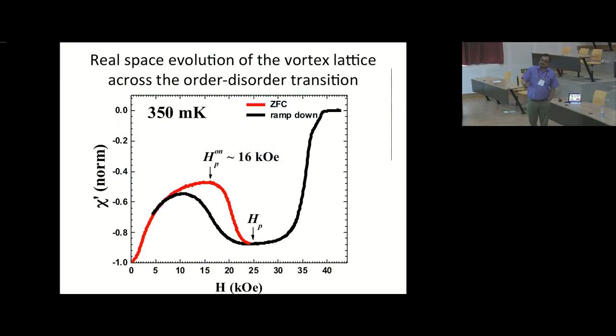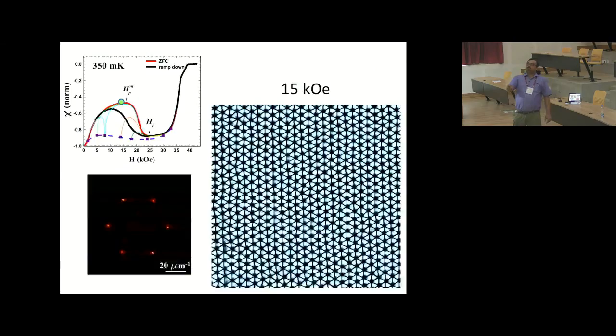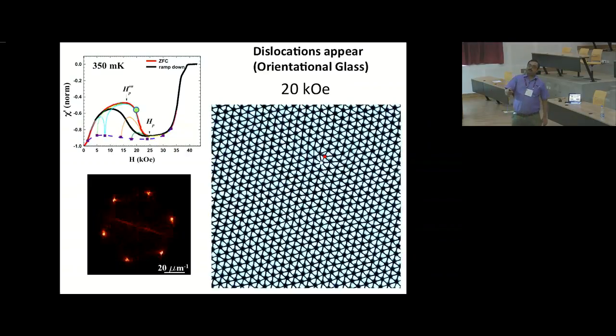This is the peak effect in our sample at 350 milli-K when we are ramping the magnetic field. So you have a peak effect which has an onset at 16 kilogauss. The peak of the peak effect is about 25 kilogauss. So now I will show you how the vortex lattice evolves. I start with 15 kilogauss. I have a perfectly ordered vortex lattice, 6 Bragg spots from the Fourier transform as expected. I go to 20, so I have crossed the onset of this peak effect.